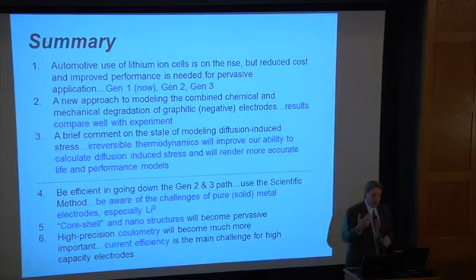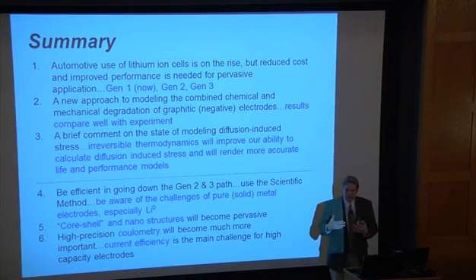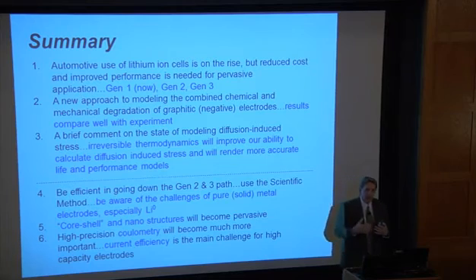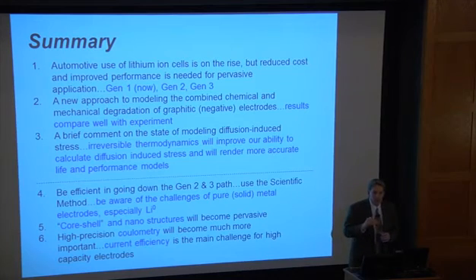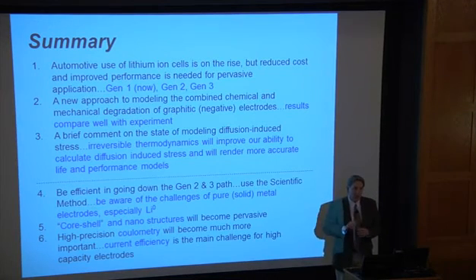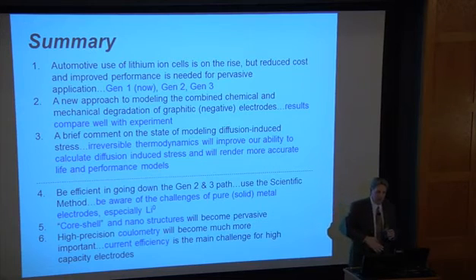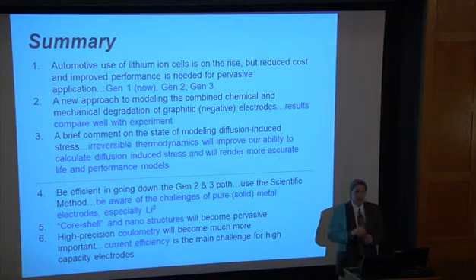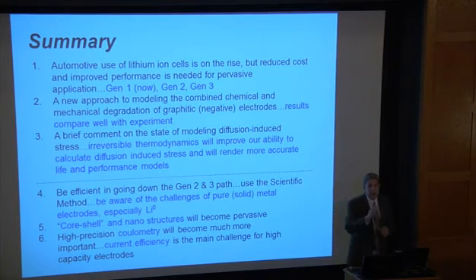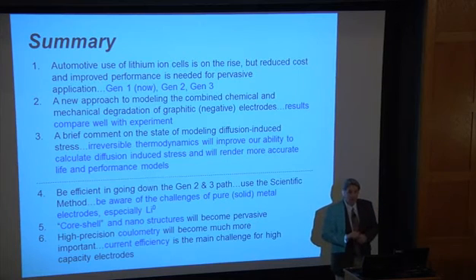So the rule in automotive, which GM adheres to strongly, is not a federal rule or anything, but the rule we have, and most companies have this, is that at minus 30 degrees centigrade or above in temperature, no customer needs to have assisted start to drive away with their vehicle. Now, if you go below minus 30 degrees centigrade, which is really cold, then you have a block heater for conventional engines, or you have some assistance in order to get the vehicle going. So when I say work, yes, at minus 30 degrees centigrade and above, they all will perform their functionality. And that's what sizes batteries in hybrid vehicles, the minus 30 degrees centigrade requirement. That's why they're much larger than they really would be otherwise.